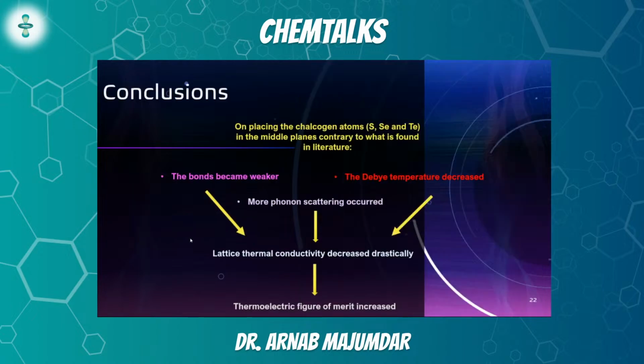Now, the conclusion from this work is that when we just flipped the atomic positions, in the conventional system, we saw that the group 13 elements occupied the inner planes and the chalcogens occupied the outer planes. But in our system, we just flipped it and we saw that the bonds became much, much weaker. The Debye temperature decreased significantly. The phonon got scattered even more. The anharmonicity increased a lot. Therefore, the lattice thermal conductivity decreased drastically, and as a result of which, the thermoelectric figure of merit increased extremely as well.